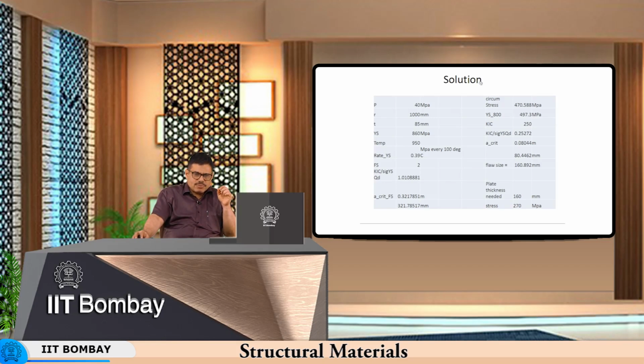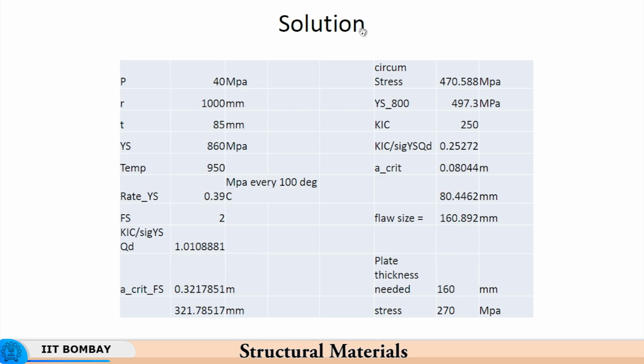Okay. So, this is a critical flaw size. Now, here A critical is 80.444. Since it is an internal flaw, the flaw size is taken as 2A and therefore, it is 160.892 millimeters. And so, for this flaw A critical to be greater than the plate thickness, the maximum plate thickness we can say is about 160 millimeters, and the corresponding stress on the structure is therefore 270 MPa, which is much less than 497.3 MPa as the yield strength of the material.